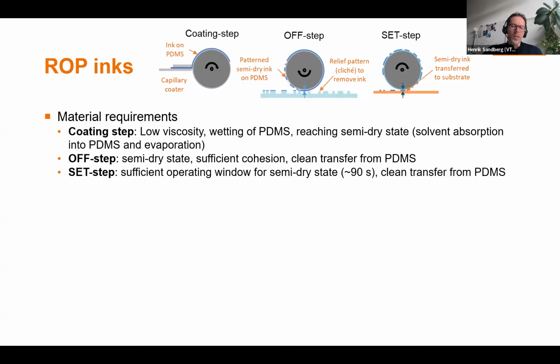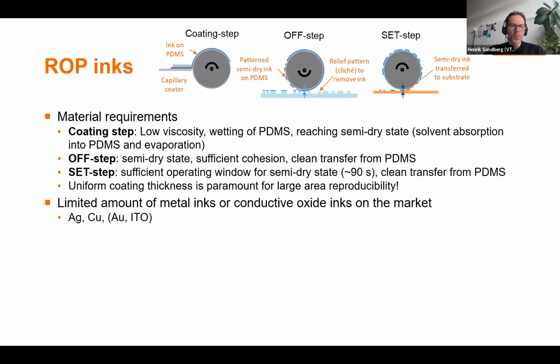And the semi-dry state now in our system is for more than 1 minute, so it's plenty of time to do the whole process under, let's say, stable conditions or continuous conditions. And as you can understand, the coating thickness uniformity is key to this whole process working. There are various inks available, but to be applicable in more devices or applications, more inks should be developed. Currently we use silver and we have some copper inks as well.